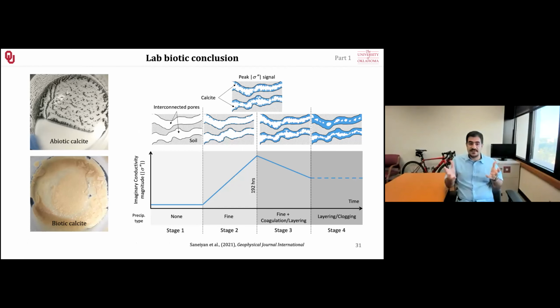So to summarize what happened here: we had a soil devoid of any calcite, and then the moment the microbes were introduced with urea and calcium-rich solution, they produced a fine precipitation around the pores and inside the pores. It reached a moment where we had a lot of fine precipitates inside the pores, and as time went by, they coagulated together and clogged the pores. So we don't have that initial increased surface area anymore. The signal initially goes up, showing we are at the fine precipitation stage, and then it goes down, meaning that we are reaching a coagulation and layering stage, and eventually reaches a plateau, telling us that we have done enough and it's the right time to stop injecting more material into the soil.